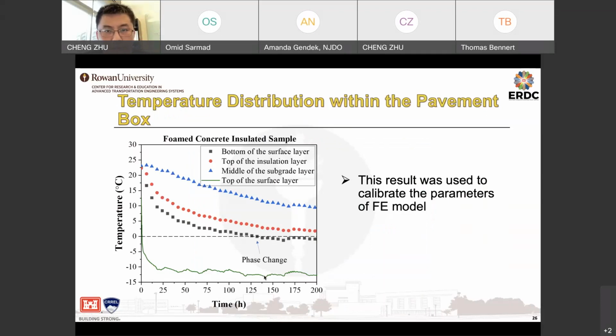These are some pictures we have for the temperature change at different depths. As you can see, the green line here is the surface temperature. It reaches about -10 degrees Celsius. And in all the different layers, surface layer, top of insulation layer, and middle of subgrade layer, the temperature is higher. Especially for the subgrade layer, the temperature is the highest because it is far away from the surface layer, and much of the heat transfer has been stopped by the insulation layer in between. So this result will be used to calibrate the material parameters of the FE model.